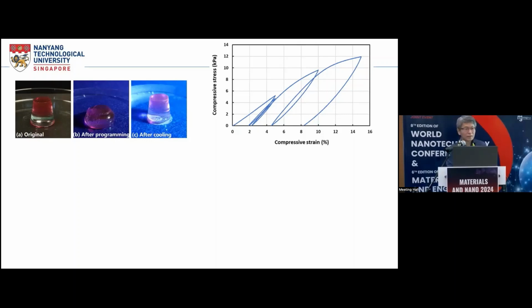water content. So we can place it inside the fridge to soften it because it becomes liquid. Certain part of it, and then compress it and take it out. So this becomes the temporary shape. This is called programming. Obviously, for most materials, we heat up the material, soften it, and then program the temporary shape. But for this material, actually, we cool it, soften it, and then we fix the temporary shape. This shape at room temperature is going to be there kind of forever.